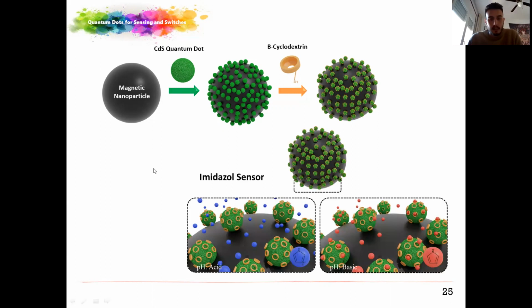we can make a sensor for imidazole, for example. In acid media, the steric impediment prevents the imidazole from going inside the beta cyclodextrin. However, in basic pH it's the opposite. The imidazole can go inside the cyclodextrin, and we can check the differences in order to know the quantity of this kind of analyte.